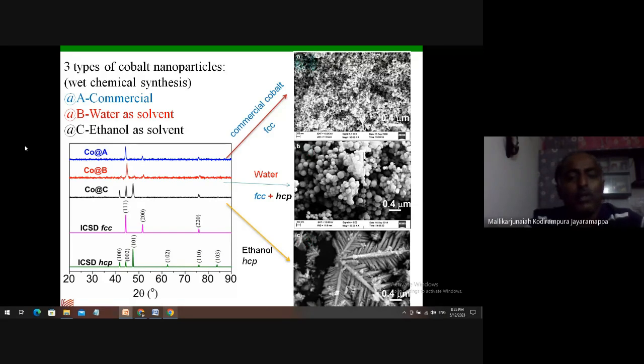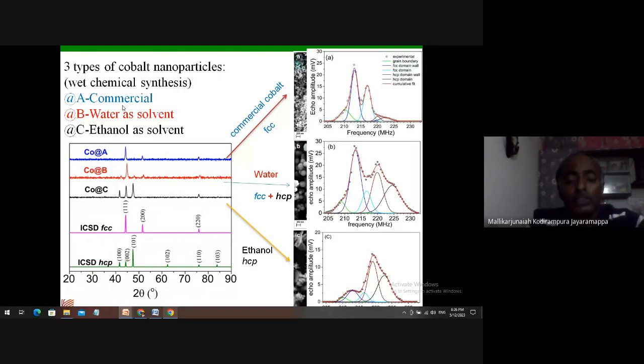As you can see, whenever ethanol was used as a solvent, we got a dendrite type structure, and whenever we used water as a solvent, it gave spherical images, and the commercial sample is already a well-known fact. We got this kind of morphology, but we can clearly see that the morphology is different. From XRD, I am not able to distinguish which phase is dominating when what type of solvent was used. For that, we did NMR of these three samples.